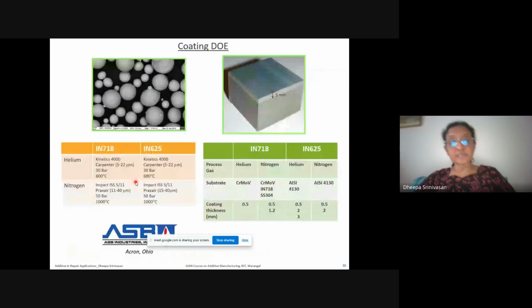So, a lot of advantage with cold spray. Basically, in this case, our collaborator was ASB Industries in Akron, Ohio, and we start with powder particles. You can see a distribution of particle size. It is almost like a bimodal distribution in this particular picture. Some of them are just about 5 microns, some of them are 30 microns.